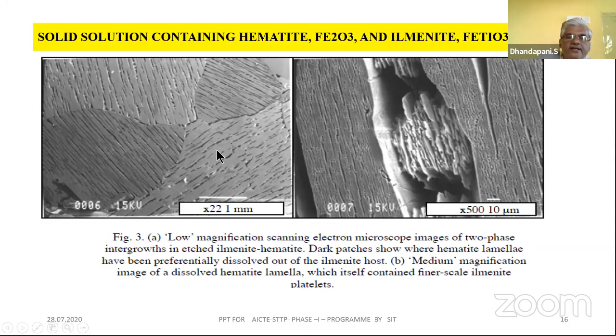The white areas are ilmenite. So hematite lamellae have been preferentially dissolved out. The black lines are where hematite is dissolved. At this low magnification scale, it looks like this. In the same picture, at 500x medium magnification, what seemed a single black line is actually a number of black lines, that is the dissolution of hematite. But here, in the same single line, due to magnification, there is a little bit of ilmenite present, so 100% dissolution has not taken place. Only after magnification can we find this.